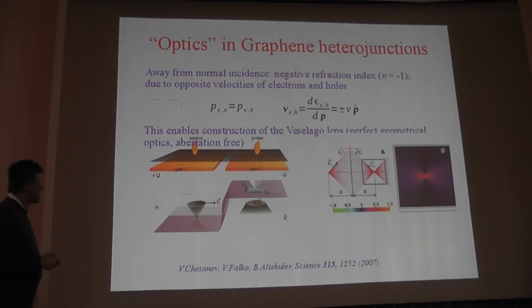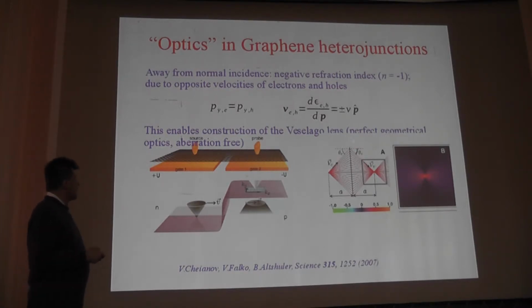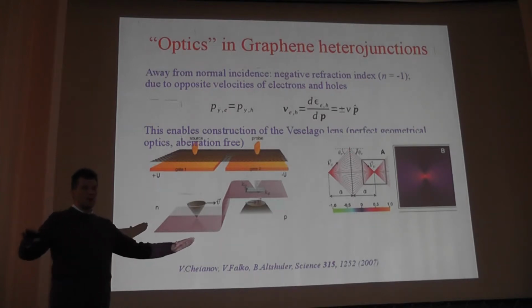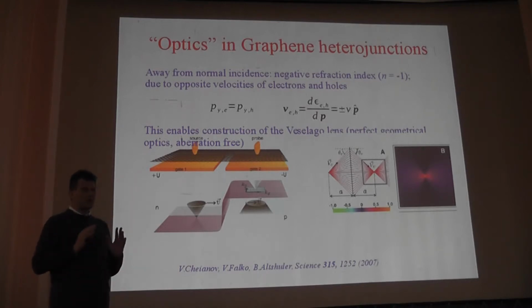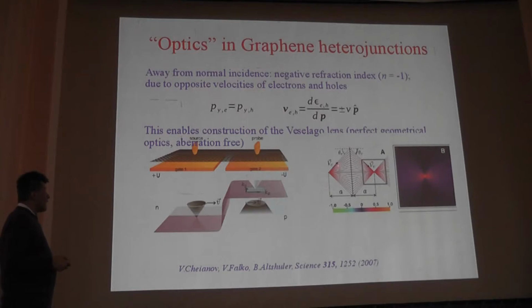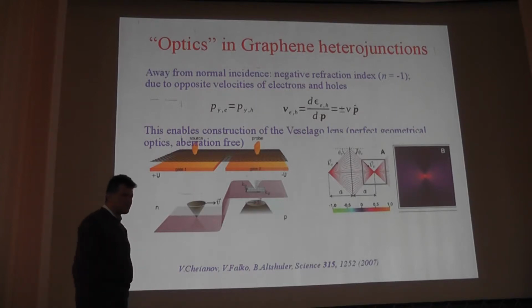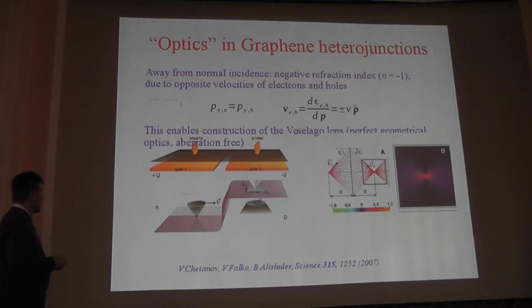If you consider particles approaching a flat junction, then the momentum component along the junction is conserved. But for electrons and holes, the velocities are opposite, so the velocity direction is reversed, and so instead of normal refraction like this, you get a refraction with negative index like this. And so one can create a lens out of a perfectly flat boundary. You don't need any curvature, as is the case with conventional lenses. So geometric optics is perfect for this type of junction, so the lens should be aberration-free. Again, that's a consequence of the use of electrons and holes and the chirality of these charge carriers.